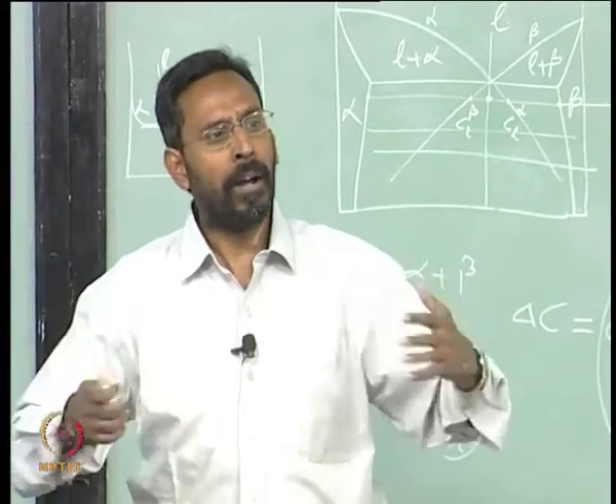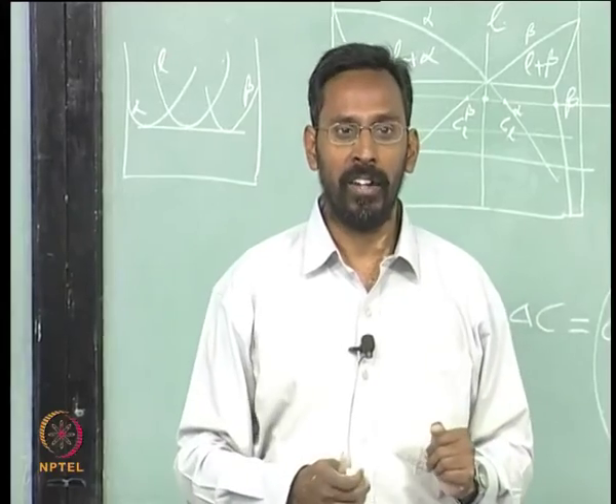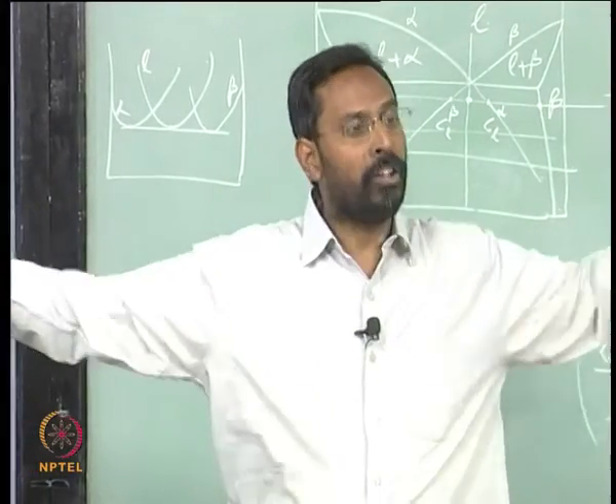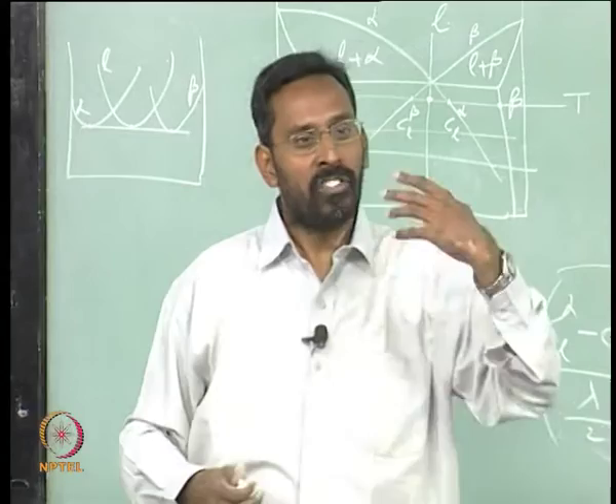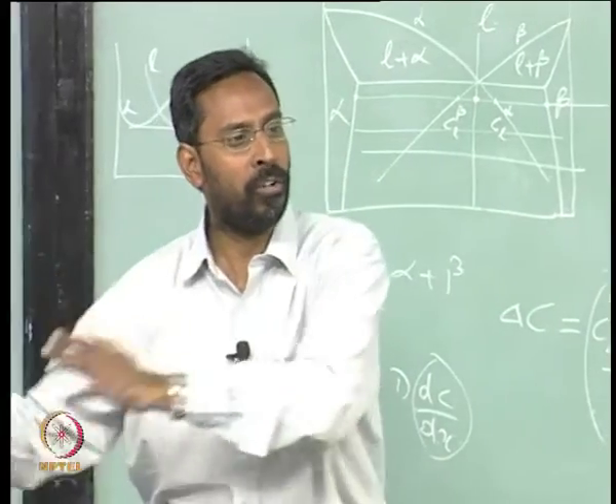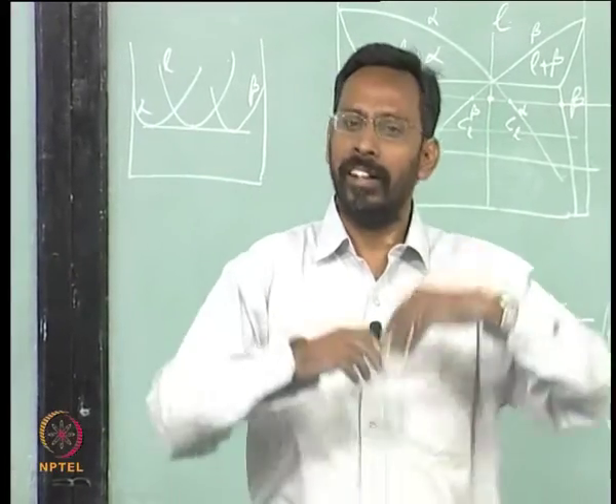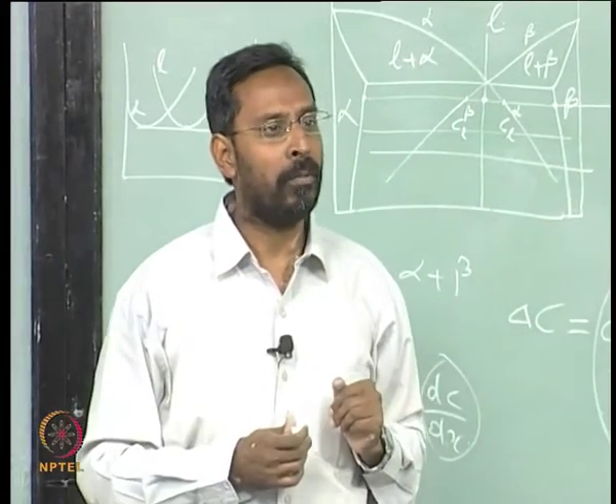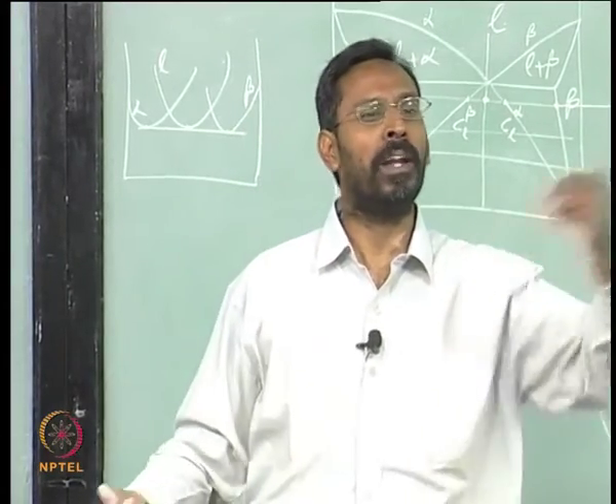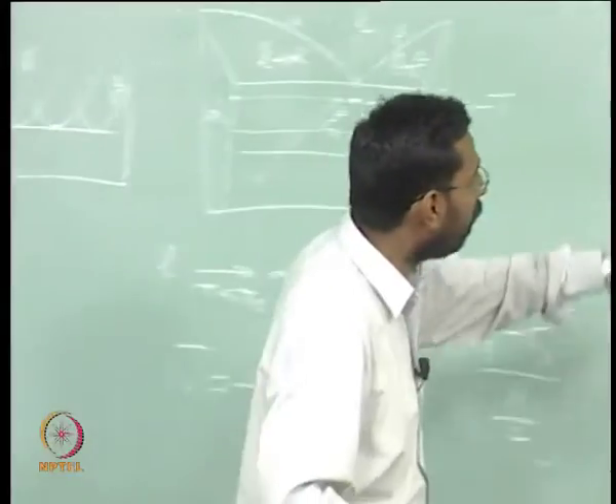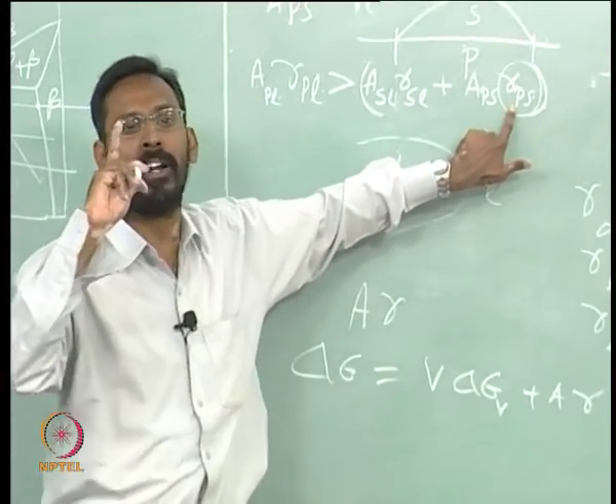But if I keep adding different cubic particles with different lattice parameters, at some stage the lattice parameter of the cubic particle becomes entirely different from that of aluminum, and even though it is cubic, it may not nucleate well. So all that is reflected in terms of one single parameter called gamma PS.